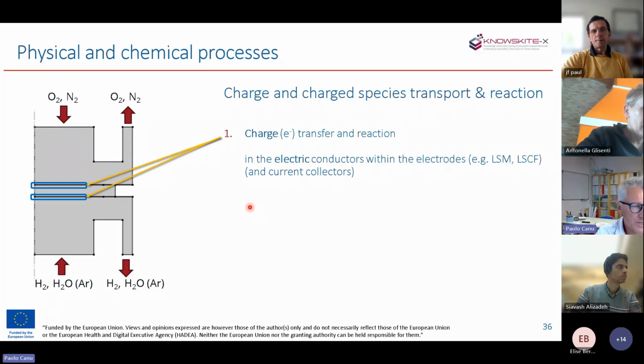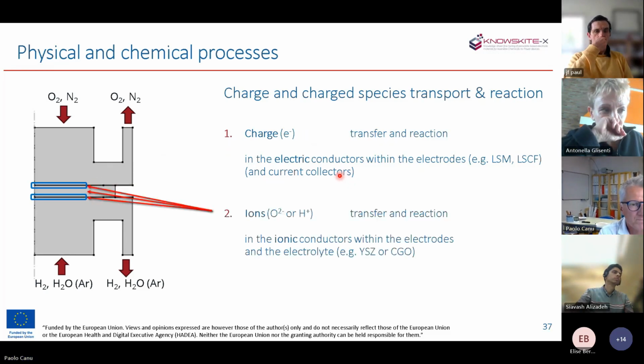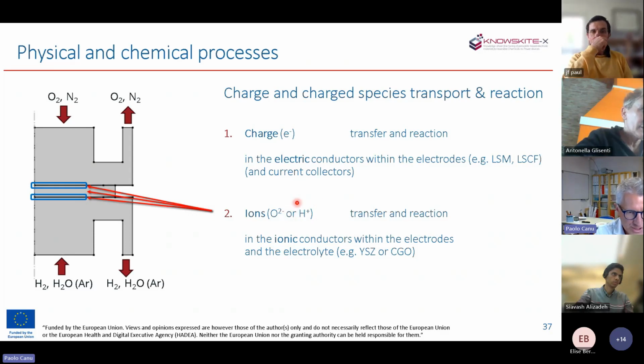Let's see another process that we need to take into account, that is the transfer and involvement in a reaction of electrical charges, which will take place within the electric part of the composite in the electrode. So in our case, it's LSCF. In many other cases studied in the literature, it could be LSM. Also the current collectors, but that is quite marginal because the transfer is too fast in the current collectors that are normally placed above the electrodes. While the ions can move within the electrodes and within the electrolytes. I mentioned that you might have proton exchange or oxygen ion exchange cells. Now we are focusing on oxygen ion exchange, but the concept is the same.